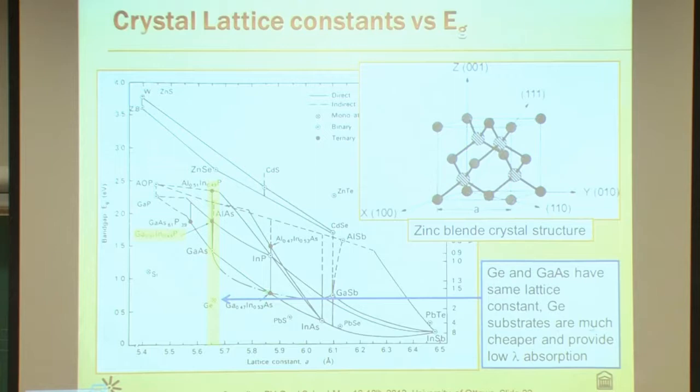That's with 50% indium. I happen to know that well because it's matched to indium phosphide for optoelectronics. But following up that line, this is just plain gallium arsenide. If you move down that a smidge, it would be like 1% indium, which is quite often seen in that middle subcell. And then the top subcell is indium gallium phosphide or gallium indium phosphide. Those can be set interchangeably, sitting up here. So we now have our three different band gaps across. Germanium is preferred because it's getting down into those lower band gaps, or sorry, higher, longer wavelengths, so we can absorb a wider portion of the spectrum, and it also happens to be cheaper.